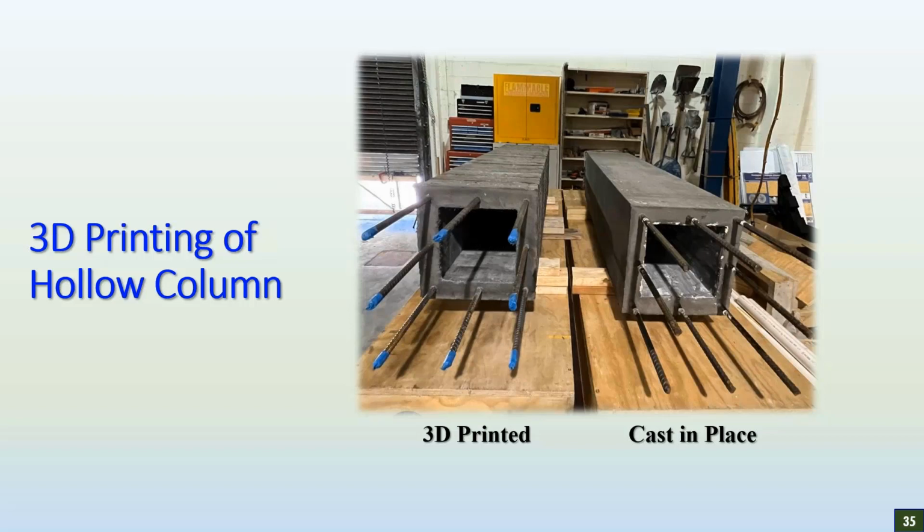We had a cost question that came in beforehand about what is the cost estimate per cubic yard of 3D concrete. Okay, let me answer it that way. I can tell you the cost of the open source. I don't want to comment on the proprietary version, other than just saying it's very expensive. For the open source, the cost of the material, including the steel fibers, can run anywhere between $500 to $800 per cubic yard. So this is just the cost of the material, anywhere between, let's say, $500 to $800 per cubic yard.